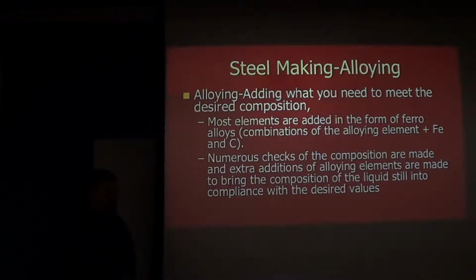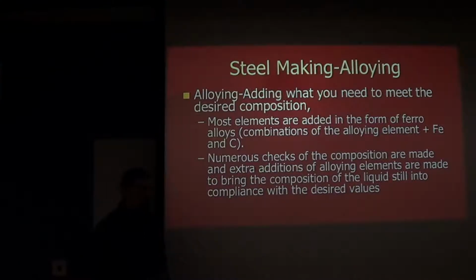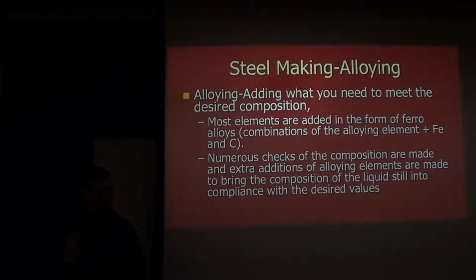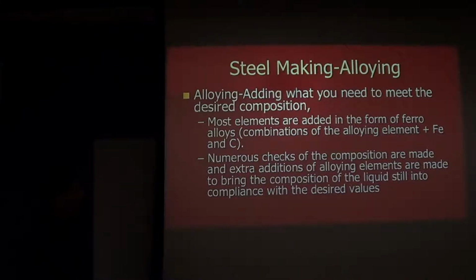But other things like nickel, chrome, molybdenum, vanadium, those are things that if they're present in the scrap, they're probably going to stay in your liquid metal. So you test it to see how much you have after you get your metal melted, and then you determine how much you need to add. So you add that in to get to the composition that you want.